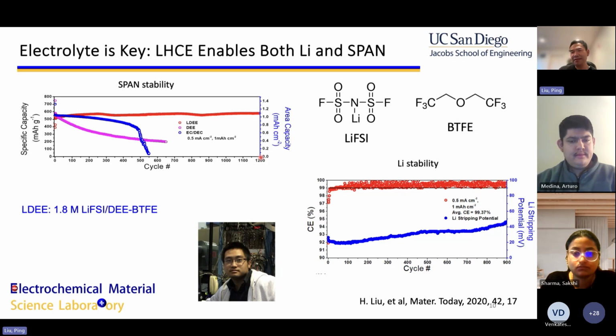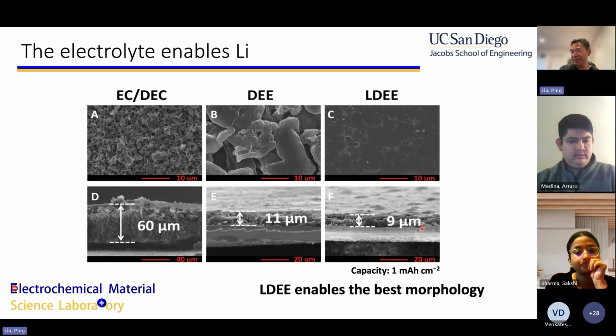You remember that was the inverse relationship between cycle life and energy density? Well, this material does not degrade. And this electrolyte also allows lithium metal to cycle very reversibly. So this is the Coulombic efficiency of lithium metal. So now we have an electrolyte that allows the cathode to cycle reversibly and allows the anode to cycle reversibly. So it sounds like we solved all the problems. Actually, we haven't, but it's progress.